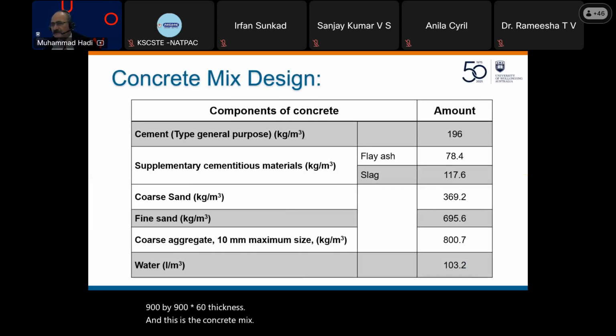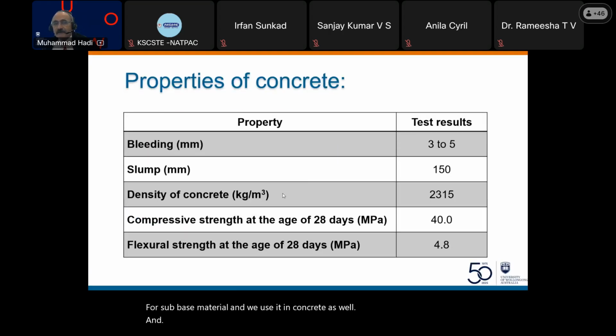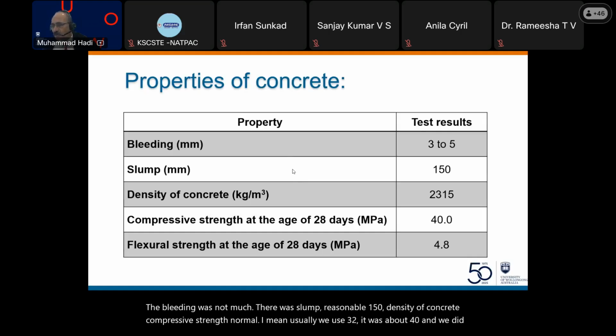So in Australia, most of the time, they use fly ash and slag as supplementary material. Indeed, in Wollongong, because there is the steel works, there's always slag. And for the last maybe 60 or 70 years, we use slag in Wollongong for sub-base material, and we use it in concrete as well. And the bleeding was not much. The slump was reasonable, 150. Density of concrete, compressive strength, normal. I mean, usually we use 32. It was about 40, and we do all these tests always.